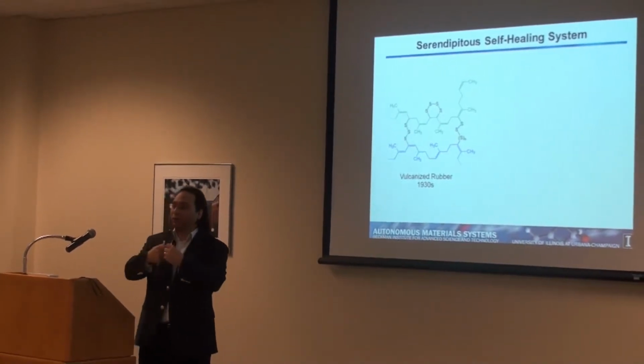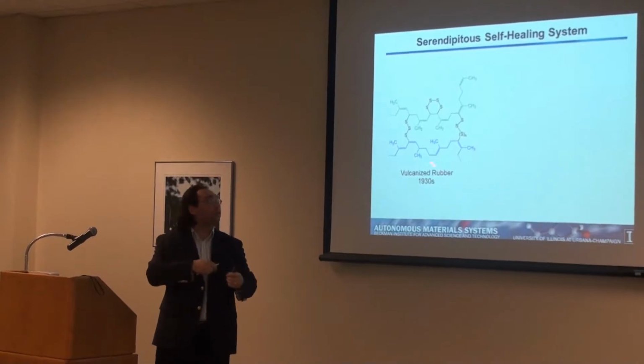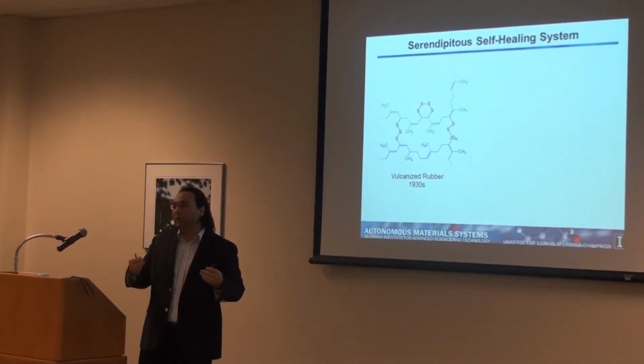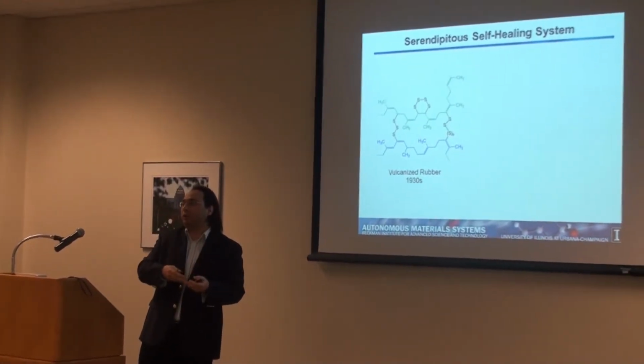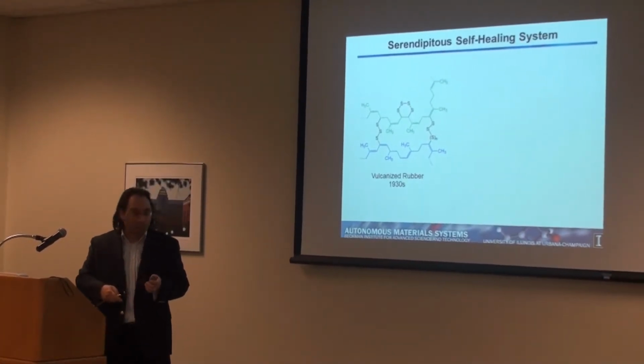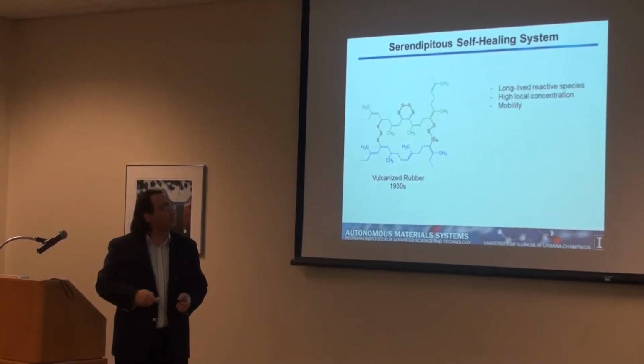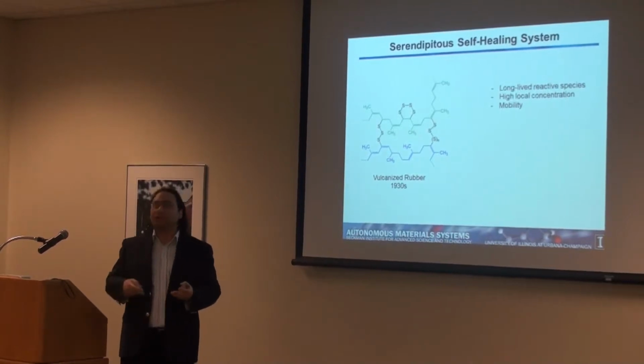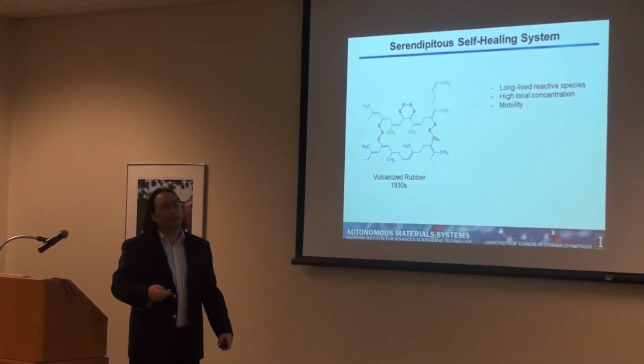These sulfur radicals can then recombine or just react with one of the double bonds and reform the bonds that were broken. So that's how the system self-heals. Learning from this system, in order to develop something that works, you need long-lived reactive species.